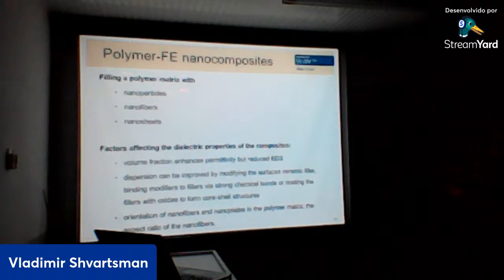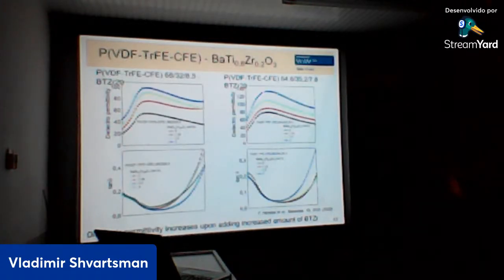People use different kinds of fillers: nanoparticles, nanofibers, nanosheets. Of course, the dielectric properties depend on the volume fraction of the fillers, on the interface between the filler and polymer matrix, and on the geometry of the fillers. Also, if we have nanoparticles, nanofibers, or nanosheets, we'll have different situations. One example is here. We have PVDF CFE with nanoparticles of barium titanate zirconate. And you see when we increase the amount of the nanoparticles, here in volume percentage, the dielectric permittivity of our materials also increases.